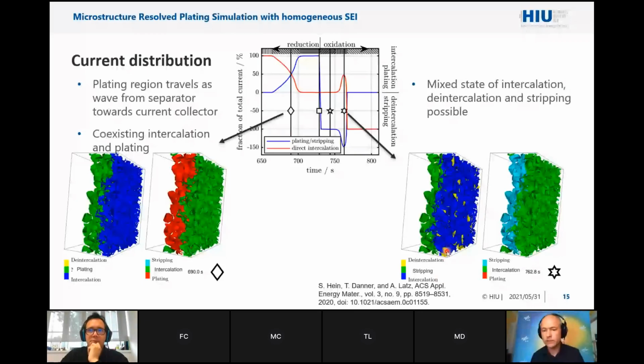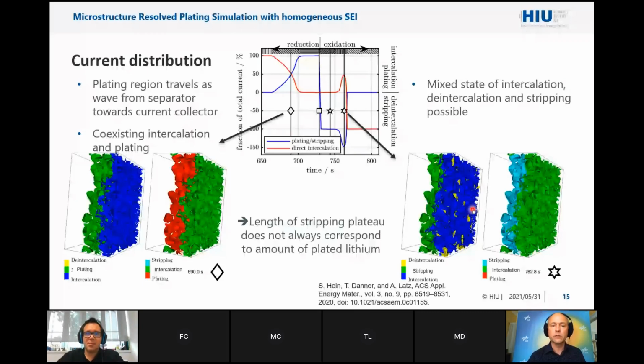So what is going to happen here actually is you dissolve your lithium, increasing the lithium concentration in the electrolyte a lot. This causes an intercalation in some part of the anode, although you are globally under a de-intercalation condition. And this phenomenon leads to the fact that the length of the stripping plateau, which is sometimes assumed, is not really indicative of the amount of lithium you have plated, since some of the lithium which is going into the solution is immediately re-intercalated in the graphite. So you have a mixed situation, stripping, intercalation, de-intercalation at the same time. So the length of the stripping plateau does not correspond to the amount of plated lithium.